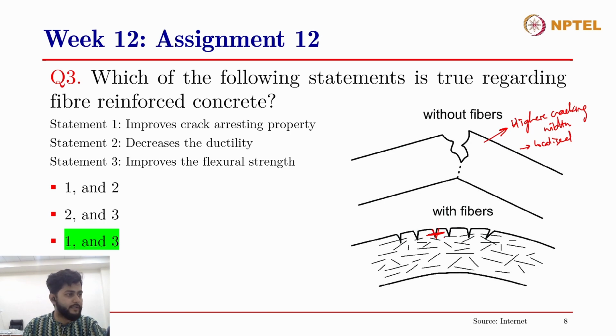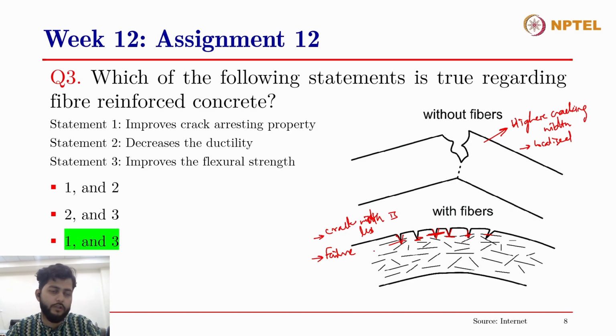Now the load is increased, and the concrete cracks at other locations. And again, the fibers present at these locations tend to bridge the gap, and therefore the crack width is reduced in the case of concrete with fibers, and also the failure is not localized. So you'll see multiple micro cracks along a range of section in the concrete, not just at a particular point in the concrete. So the failure is not localized. So the first statement is correct.